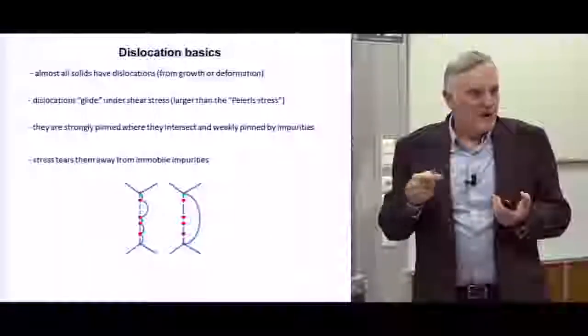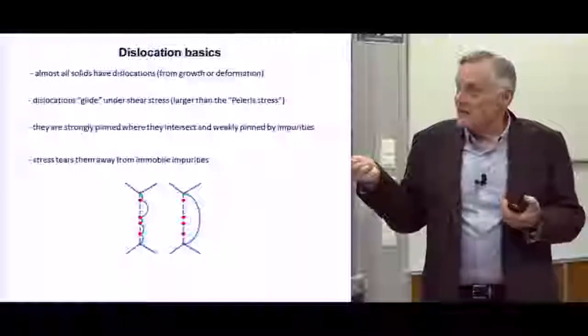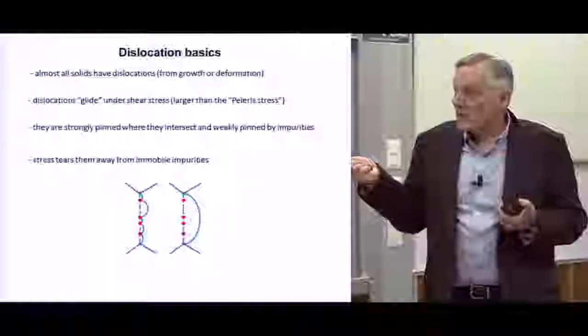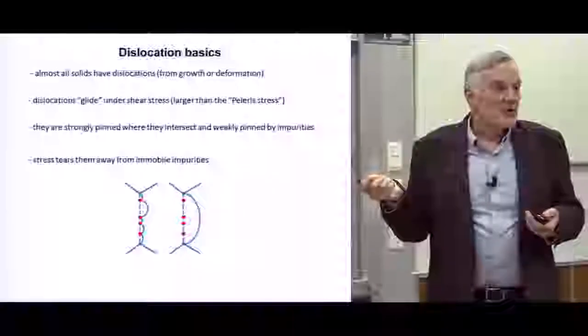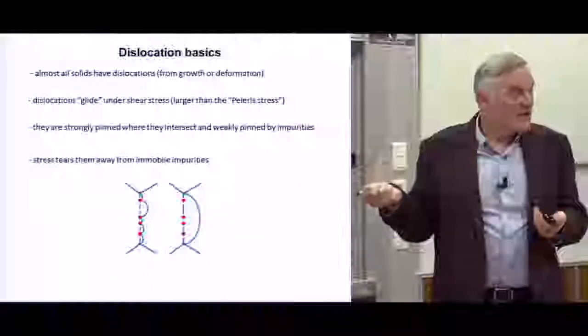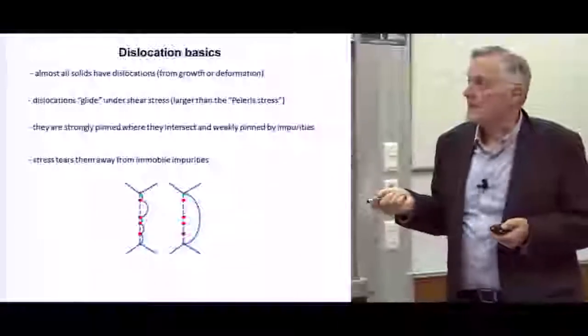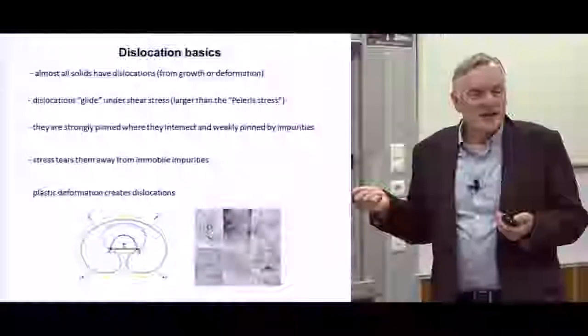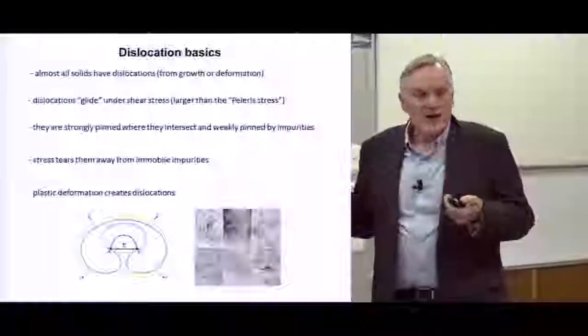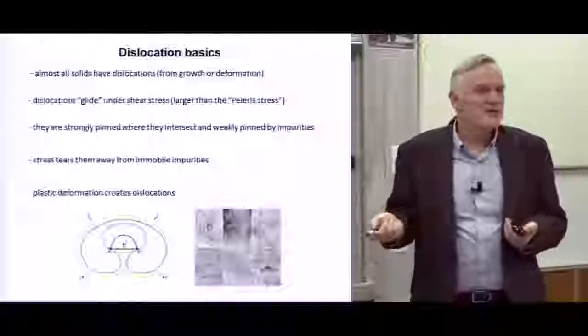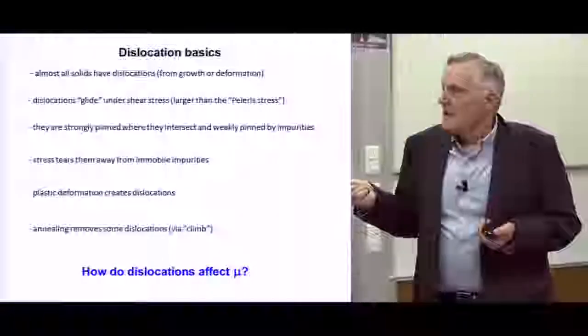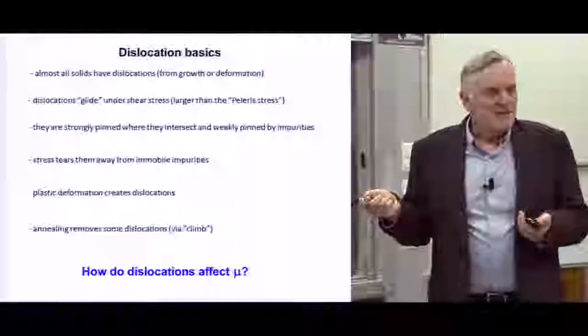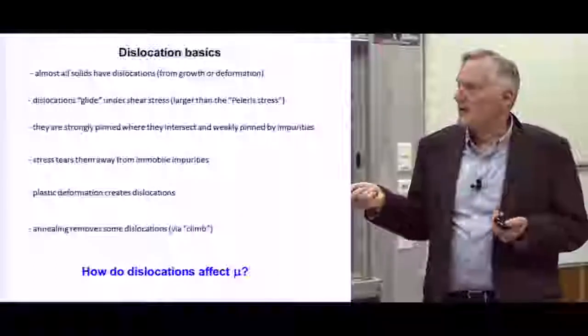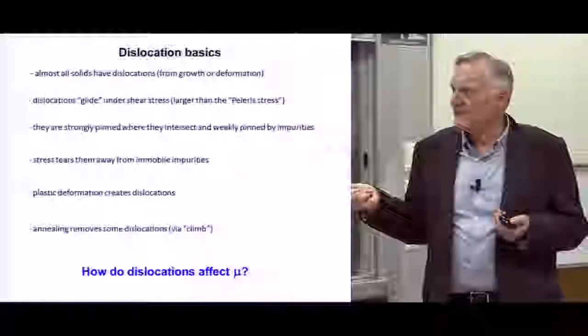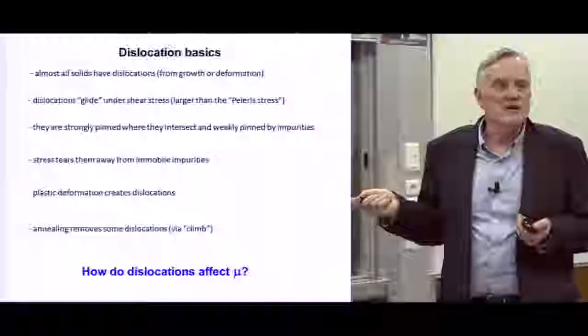However, they're not perfectly pinned. If I put a lot of stress on it, the dislocation is going to rip away from these pinning points and move freely. And that's the origin of the amplitude dependence you often see in this kind of thing. And if you really deform it a lot, you're going to start to actually create whole bunches of new dislocations, tangles of them. And if you anneal them, you might get rid of some of them. So that explains why annealing is important. And the question then is, how do they affect, quantitatively, the shear modulus?